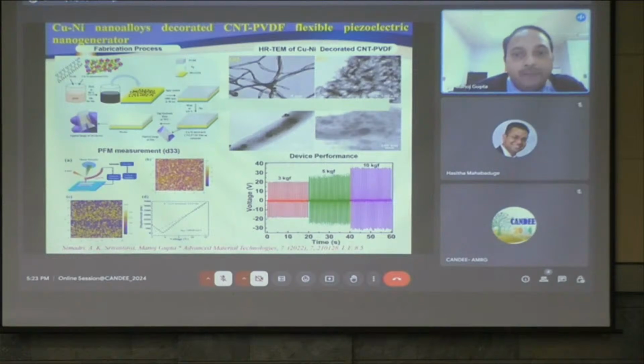So for that, we developed copper and nickel nanoalloys through a chemical approach, and we introduced these copper-nickel nanoalloys within the carbon nanotube. And we can see here, this copper and nickel was inside the carbon nanotube. So it reduced the surface energy and also allowed us to connect all the CNTs together in a better way.